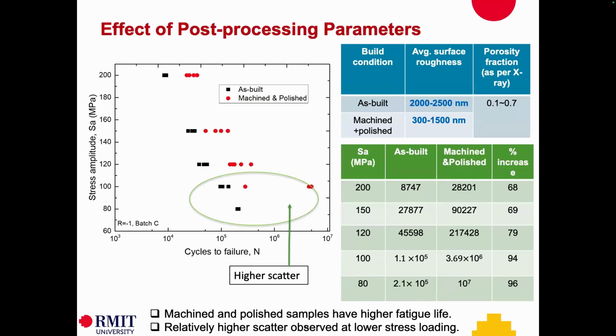You eliminate all the fatigue issues coupled with surface roughness. But in our case, porosity was very small, so there was no effect of porosity. But if you have large pores or multiple pores, even if you remove the surface roughness effect, you may not get the right answer. You may still get a lower fatigue life. So coupling of different defects is very important.